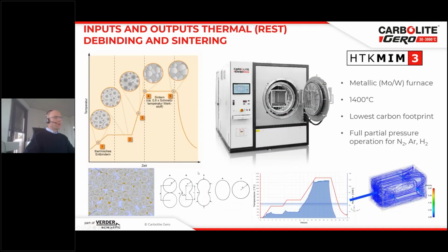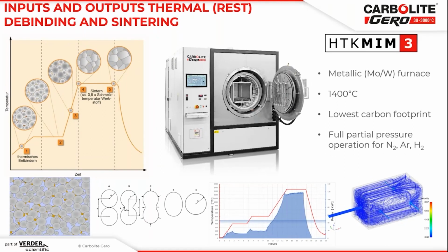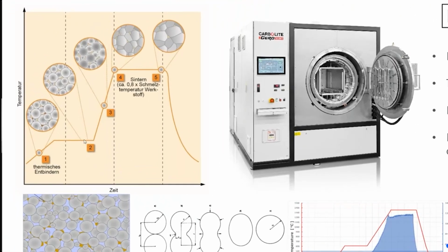I told you before, after this debinding step, with a solvent or with a catalyst, you still have the backbone binder in the system. And this backbone binder you can remove only by a thermal debinding step. And that is why the sintering furnaces have to perform two things. First of all, they need to remove the backbone binder. The orange parts here need to be removed, and this normally happens between 400 and 600 degrees C.